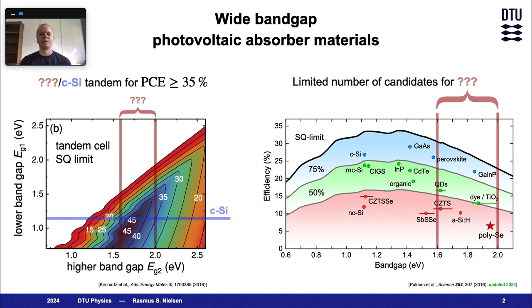However, the ideal photoabsorber for the top cell should then have a bandgap within the range of 1.6 and 2.0 eV, and as it turns out, the list of potential candidates is actually quite limited. Among the high performance candidates, we have perovskites, but stability and toxicity concerns are still to be addressed. And then we have gallium indium phosphide, which is very expensive to manufacture, and it contains indium, which is a critical material. And then we have a few candidates which, in spite of decades of research, have yet to demonstrate